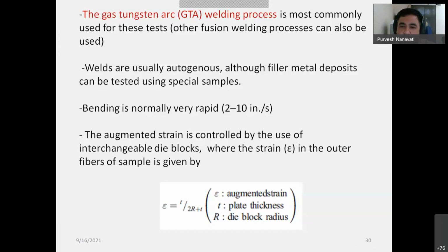Because if you employ a lesser radius die, then it will have more strain, right, on the material or the test coupon. Likewise, you change the die block radius, and accordingly your strain level will also be changed. So this strain is formulated by an empirical formula: e is equal to t divided by twice capital R plus t, where small e is the augmented strain, right? Augmented strain, where small t is the plate thickness you apply, and R is the die block radius, right?